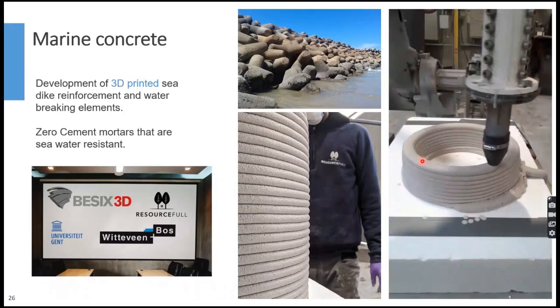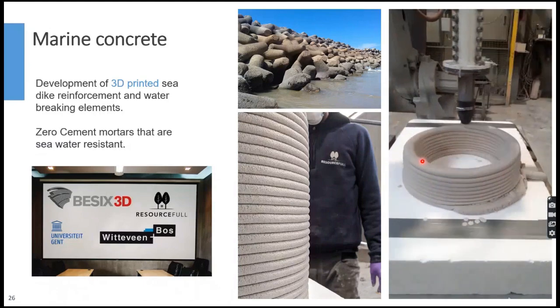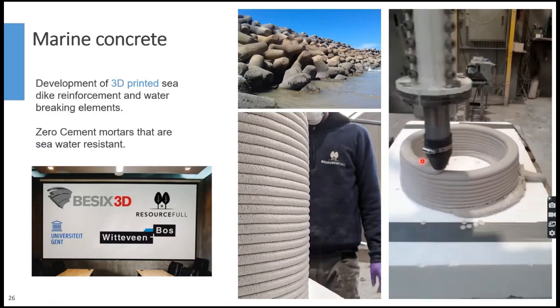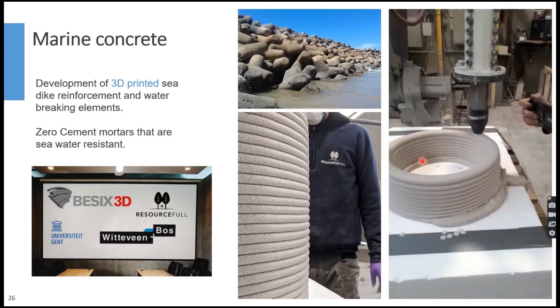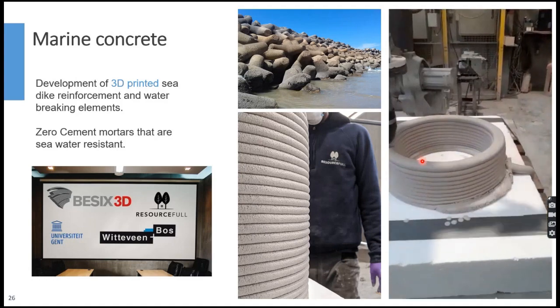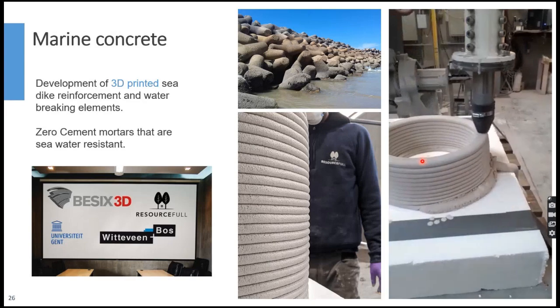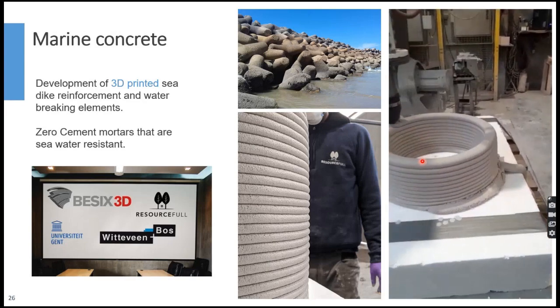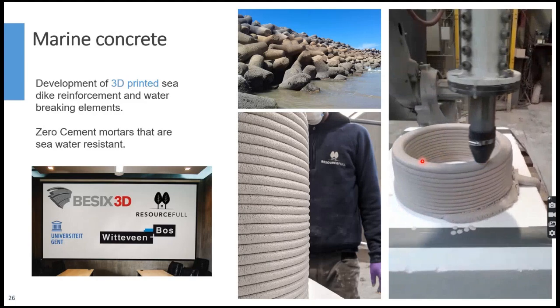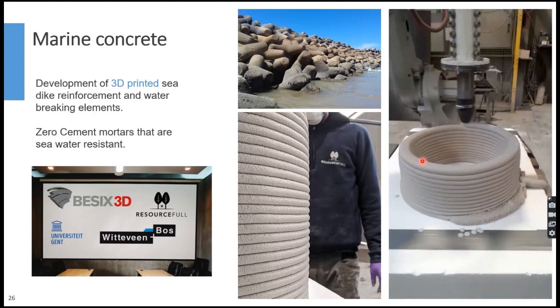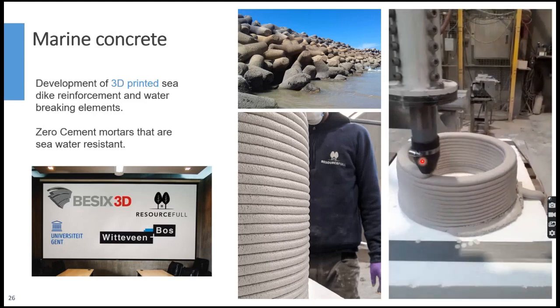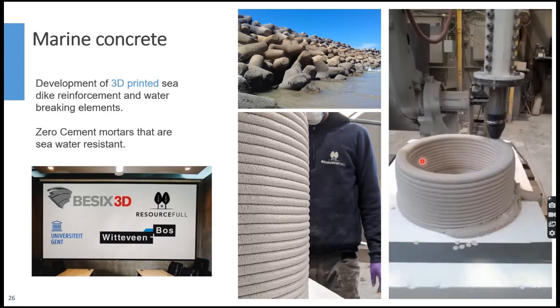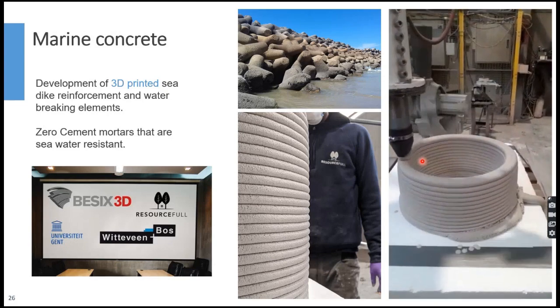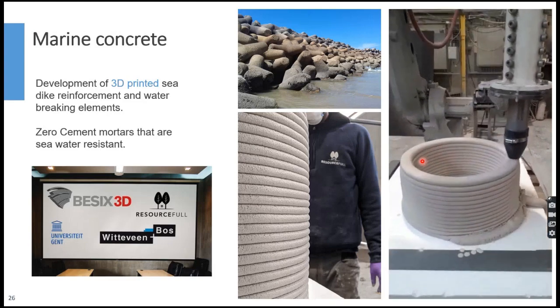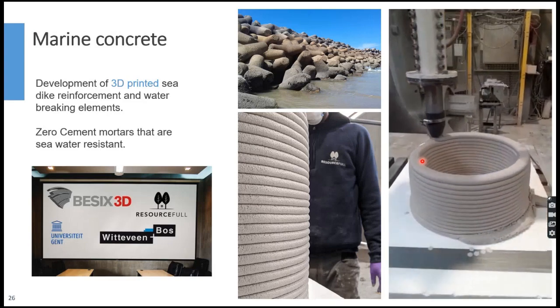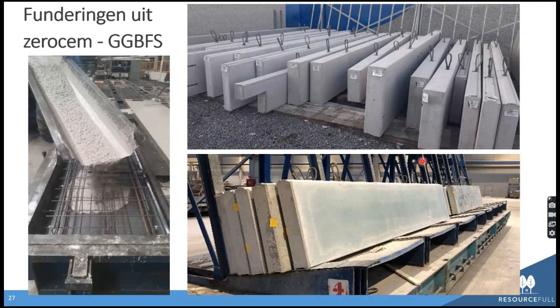3D print mortars is also a bit of a hype in some materials and some products. I think we believe in it, but if you 3D print, you should do it, let's say, with an eco mortar, because in the average 3D printing mortar, there is 600, 700, 800 kilo of Portland cement. Yeah, then the people who claim that they can use a little bit less material, yeah, but in an average ready-mix concrete, there is maybe 100 kilo of clinker. Then you already need to use a lot less material to be more eco-friendly.